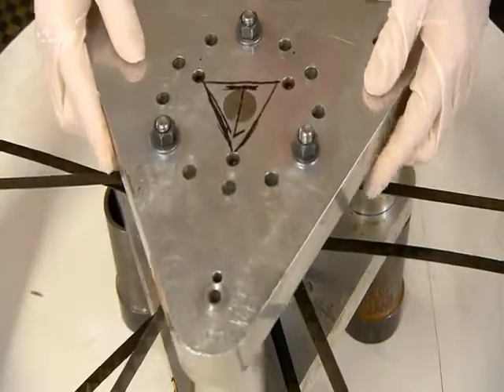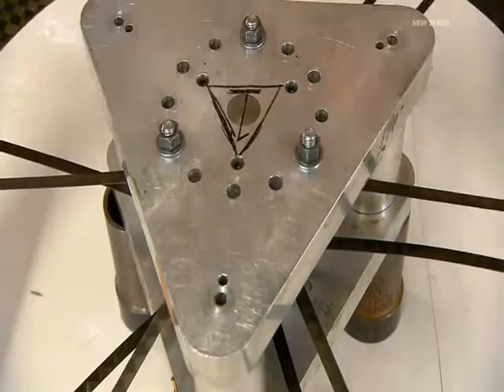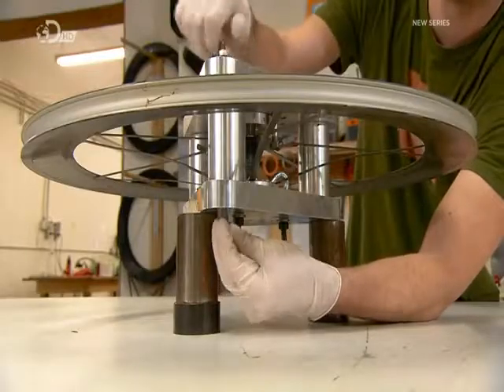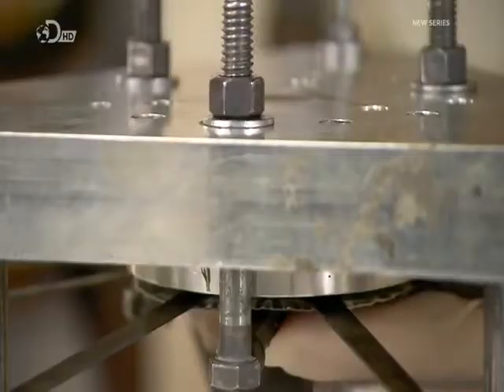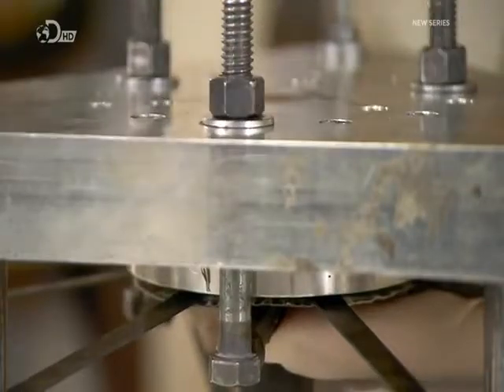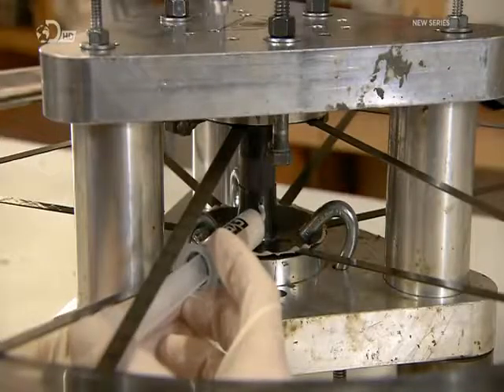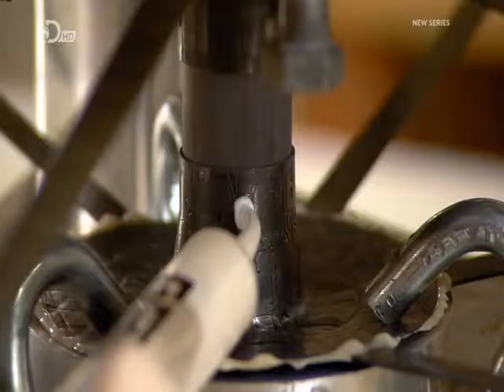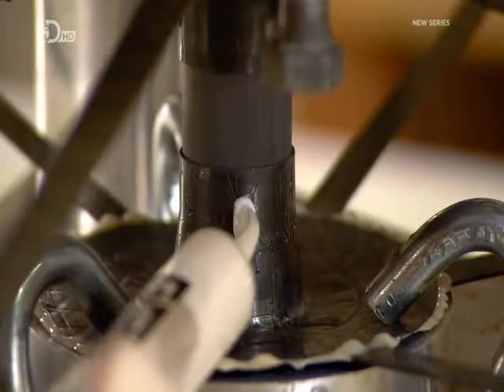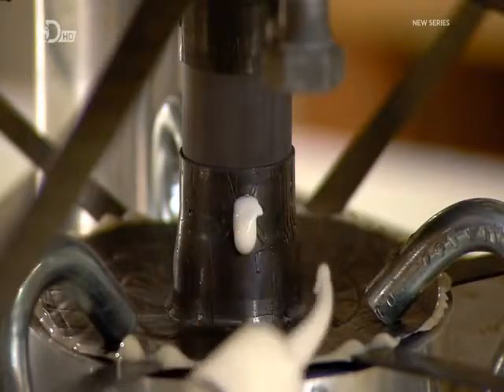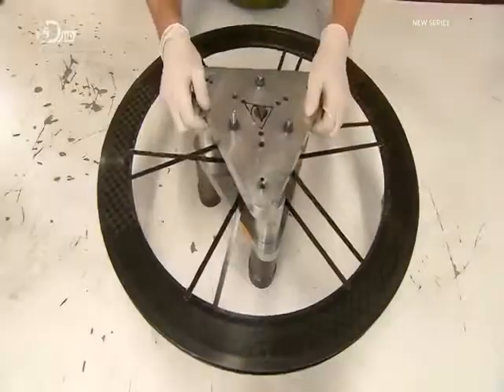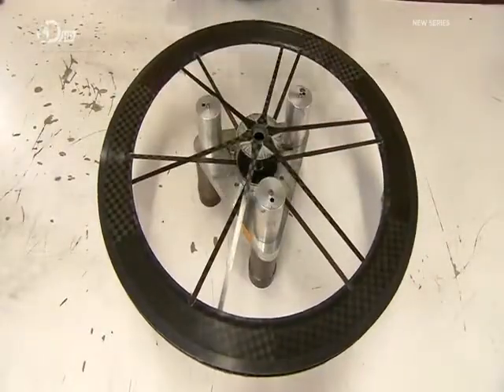The technician locks the bike wheel in a fixture that lightly stretches the spokes, and this creates the necessary tension and rigidity. Once he's satisfied with the tensioning, he applies resin adhesive through a hole in a hub flange. 2 hours in an oven sets the tensioning, and he removes the wheel from the fixture.